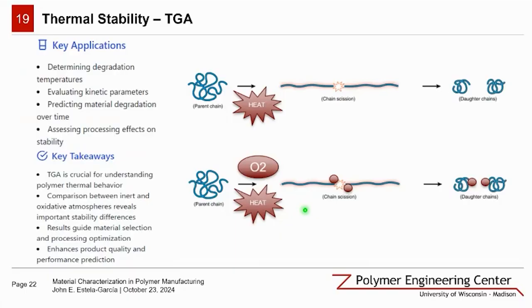So the applications for TGA are extensive. You can use it to determine critical degradation temperatures. You can use it to evaluate kinetic parameters. You can use it to assess the impact of processing on your material stability. You can use it to determine how the material degrades over time and predict that. The comparison between inert and oxidative atmospheres allows us to reveal stability differences, which is invaluable when you're trying to determine what material to utilize and how to optimize your process.